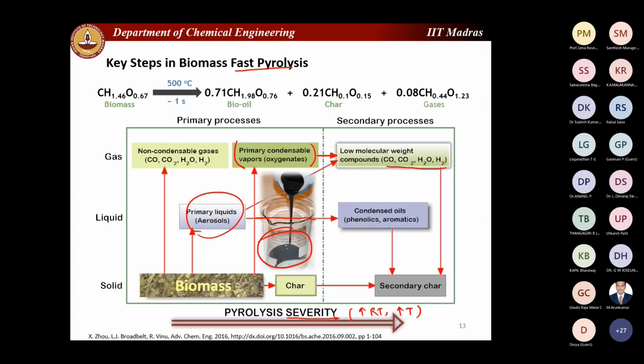Okay, so typically coming to the pyrolysis method of converting lignin to valuable chemicals. So pyrolysis involves slightly higher temperatures of the order of 500 degrees, and that really involves three different phases in which the reactions could occur. So you take a solid biomass, and when you subject it to a fast heating rate, it can actually produce the primary liquids or aerosols, right? And these aerosols, when you're going to subject them to a much longer residence time or a much higher temperature, they can undergo secondary transformations and produce condensed oils or phenols and aromatic hydrocarbons. And you can also have a parallel pathway to form low molecular weight compounds like the permanent gases.